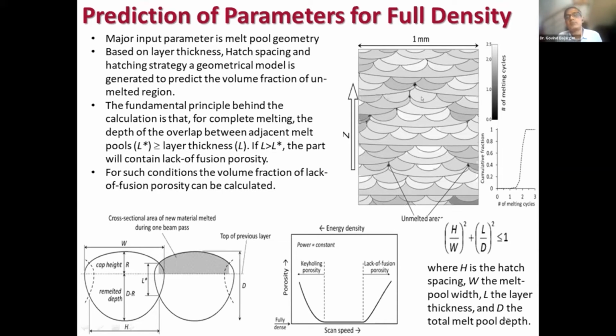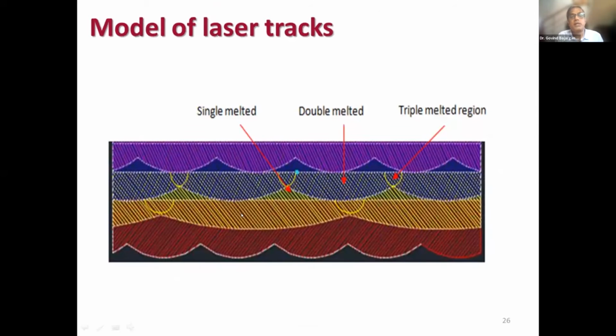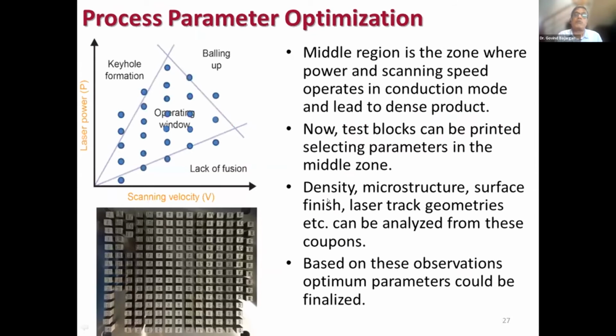So by varying the hatch spacing, we can control the zones where lack of fusion is happening. Here we modeled, and we have shown here that there are zones where single time melting occurred, there are zones where double melting occurred, there are zones where melting has happened 3 times in the process. So once we have this data, now in the optimized window, we have to finalize the parameters.